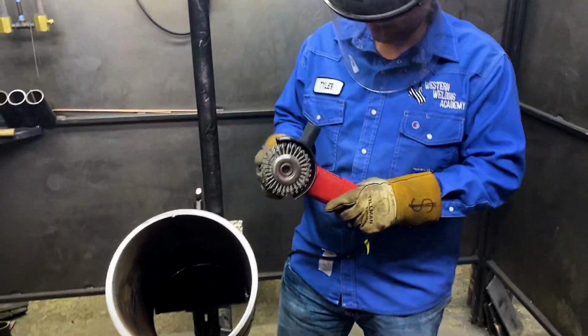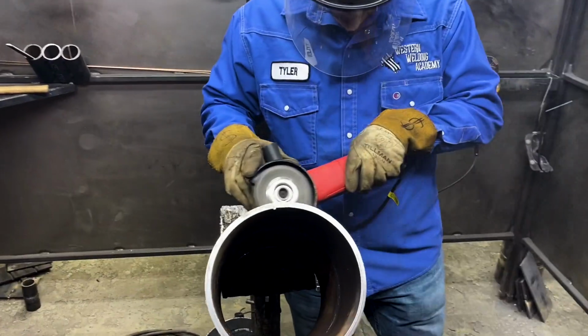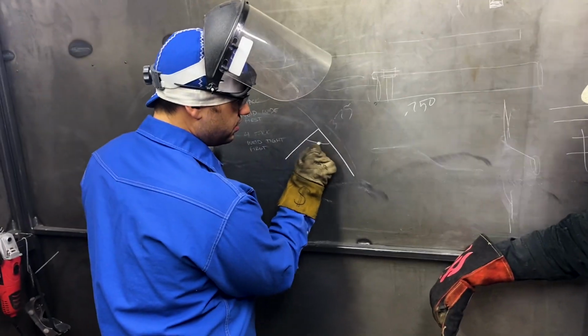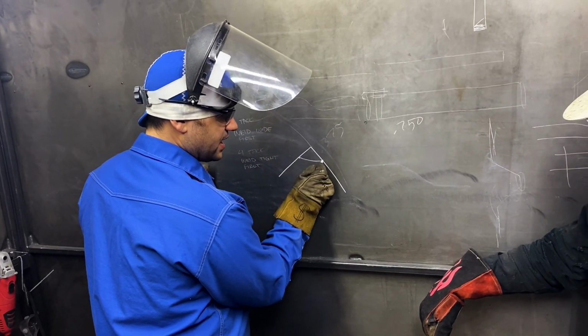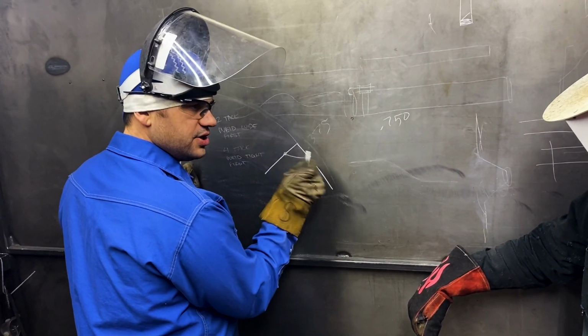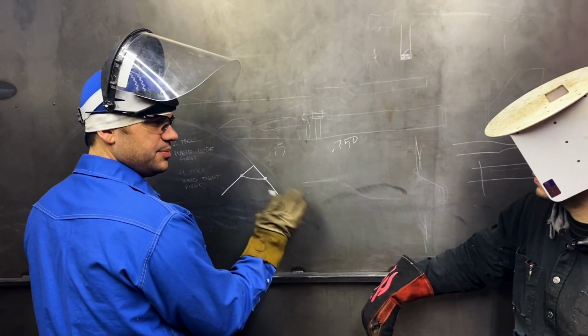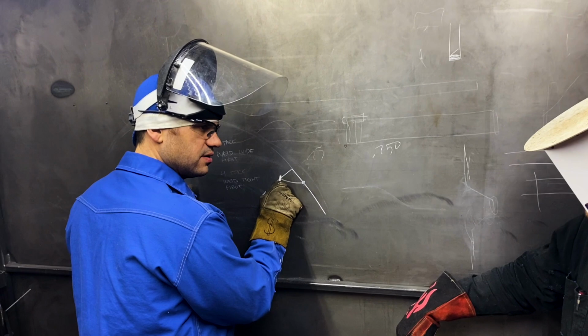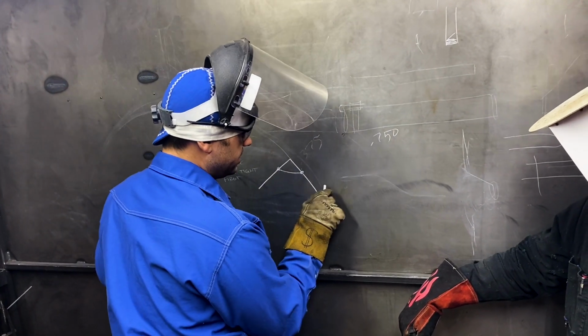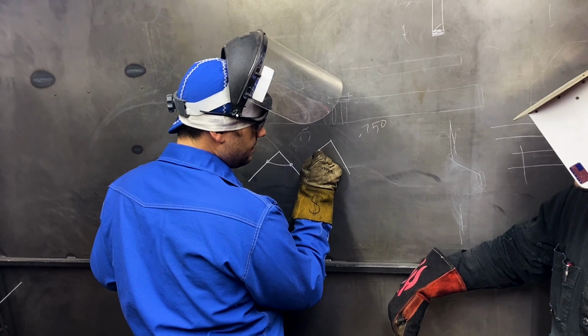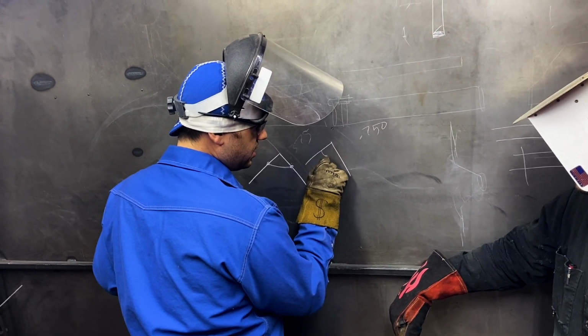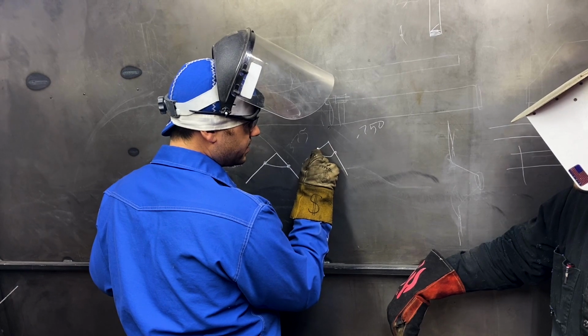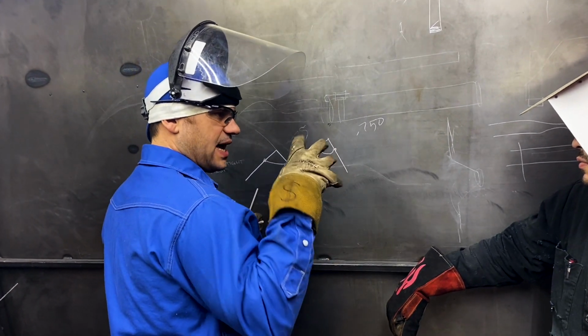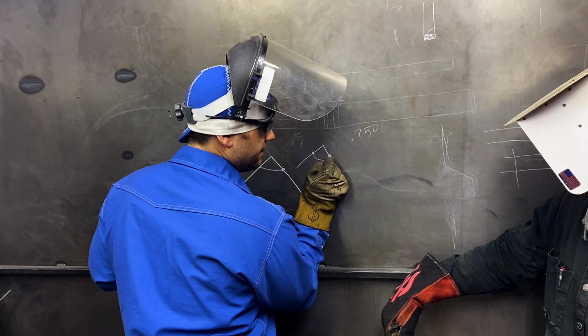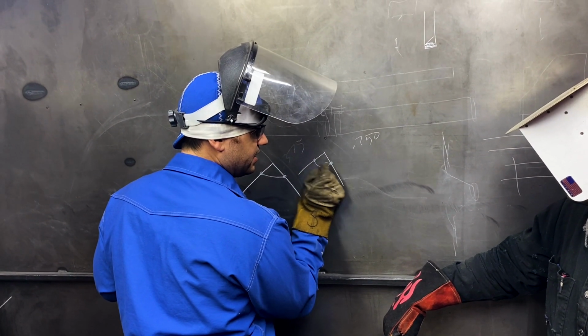We'll knock the slag off, take a look at it. When you put 7018 on an inside corner, it wants to trap slag on the edges. The way to keep it from doing that is by holding your sides longer. Because if you don't hold the sides long enough, you'll get a little bit of undercut right here, which is like a little trap that hangs onto that slag. And so if you don't hold it long enough, you'll have just a dab of slag here and here.